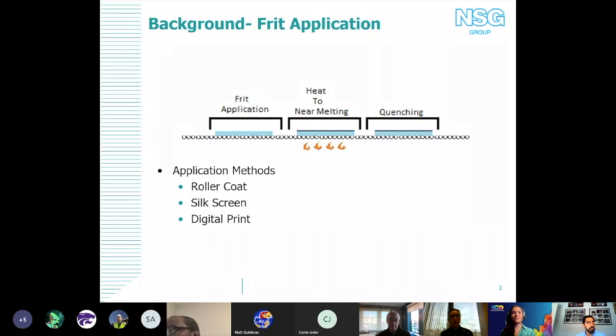the glass. And the frit has these glass particles or ceramic glass particles in it that after it's applied, you put it into your tempering furnace, and it's heated to a near melting temperature, not quite melting, but enough that whenever it's rapidly cooled, the ceramic frit is now fused onto the surface of the glass. So they're now one cohesive element, and it can't be scratched off.